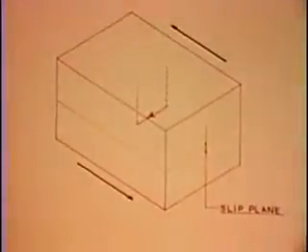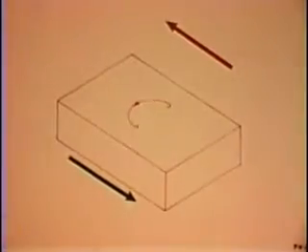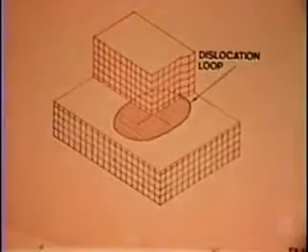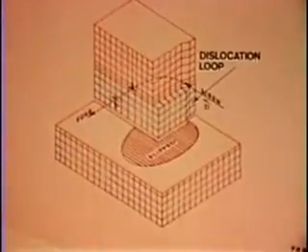The bulging dislocation segment minimizes its energy by always being an arc of a circle, like a section of a bubble bulging out from a pipe. Once the dislocation becomes semicircular, the stress provides enough energy for the dislocation to bulge into a free loop, like a bubble expanding and separating from the pipe.